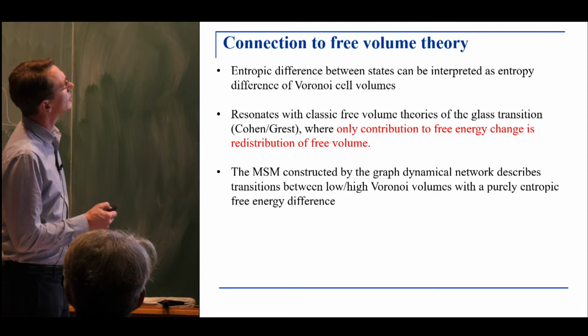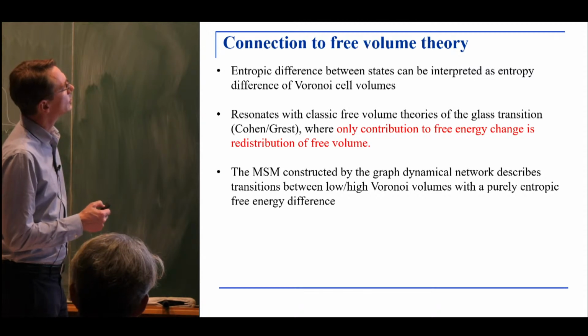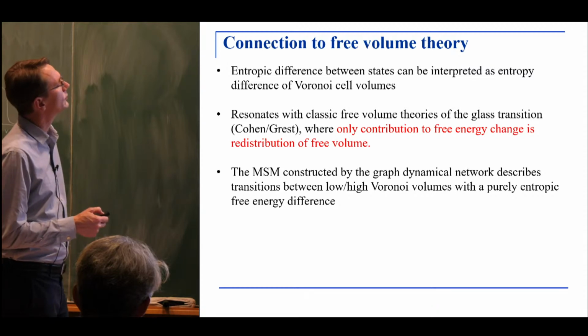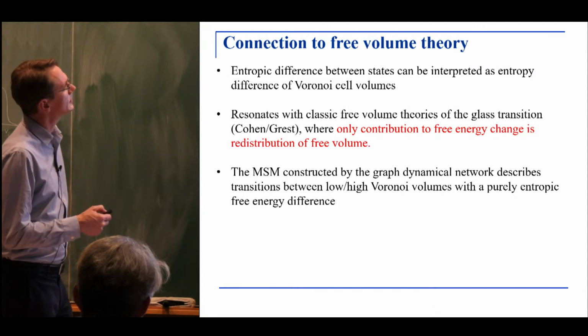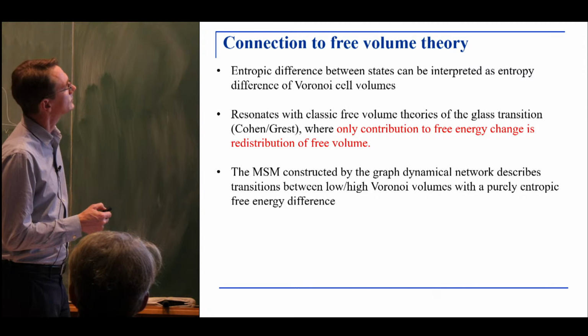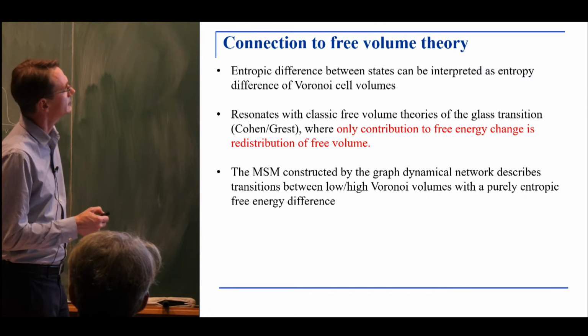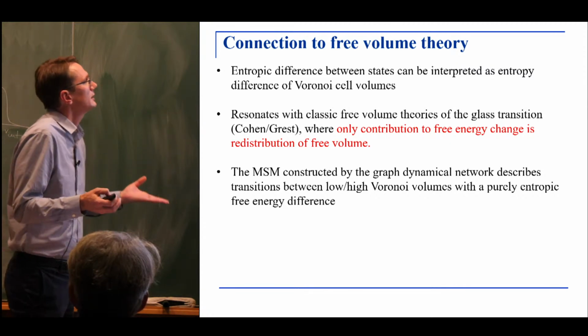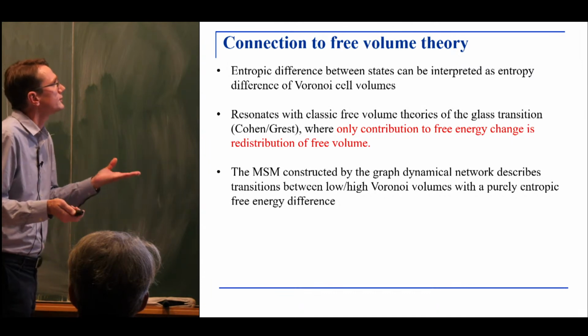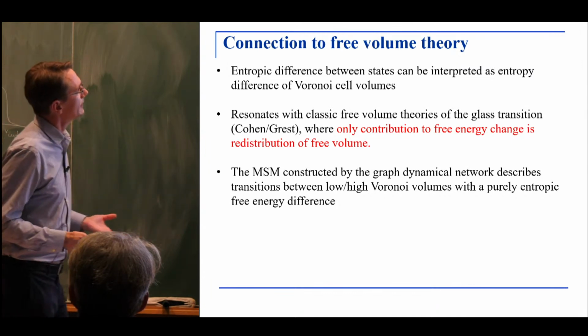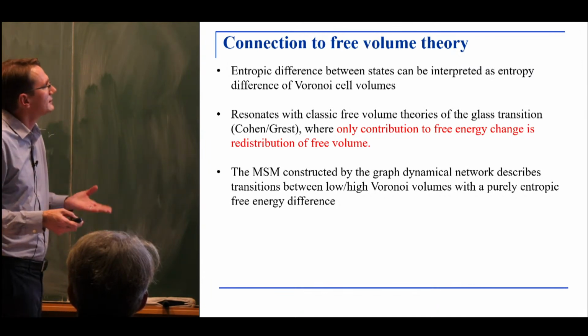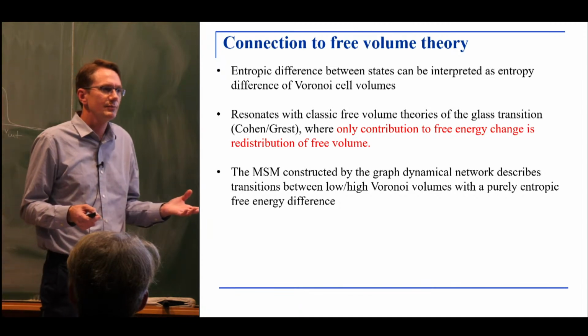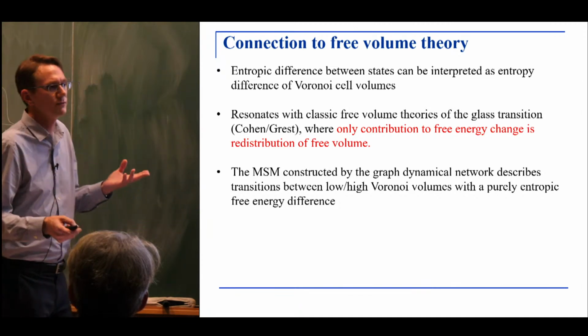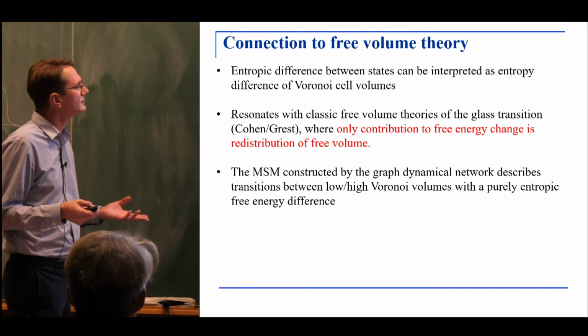What we found in our model here is that there's an entropic difference between the states, and if these states are indeed Voronoi cell volumes, then one would conclude that the only difference in free energy between these different cells comes from entropy. And my understanding is that this is kind of the picture that was painted in the 60s and 70s in these free volume type theories of the glass transition.